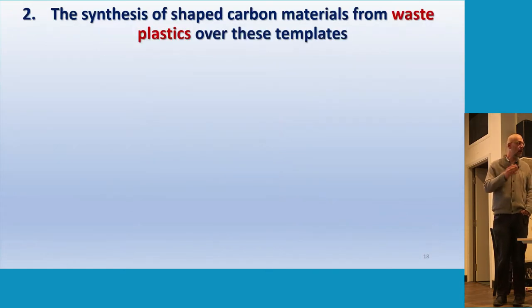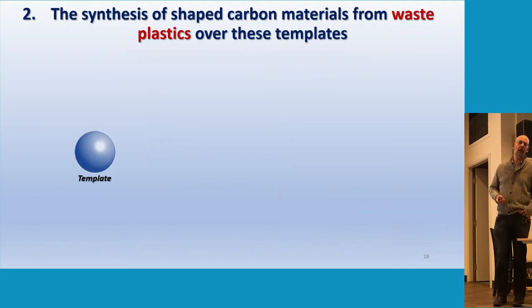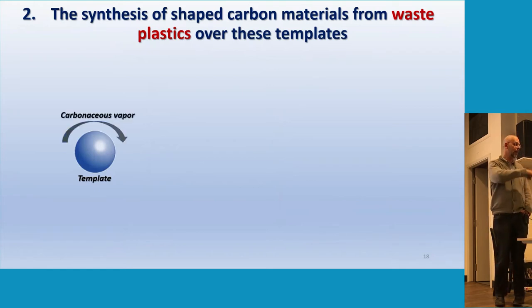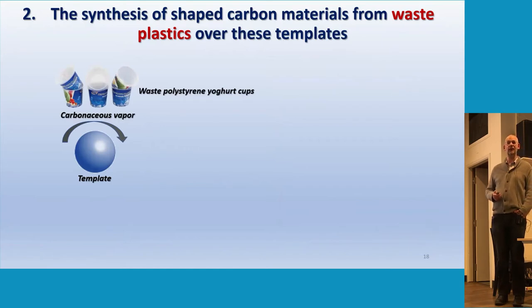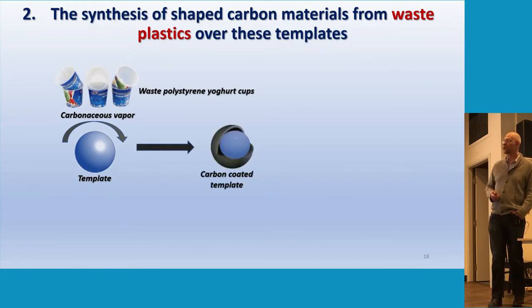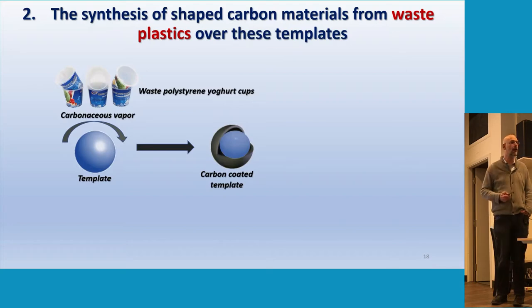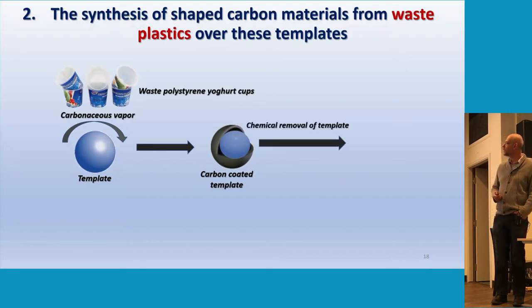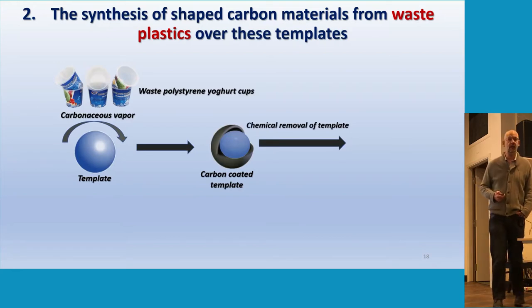The next step is to actually make these carbon structures that we want to use, because we want to put them into other plastic materials to make composites for functional reasons. What is a template? Well, I said to you it's a shaped material. In our case, the copper carbonates are known to form either micro or nanospheres. So you take the template and you pass a carbon gas over it. What we found before in previous research in the laboratory is that you can use waste plastics as the carbon vapor. We use polystyrene. This is an NSERC funded project that we did. And when we did that, we were able to coat the template with carbon. In that case, it was a calcium carbonate, but we're going to do the same thing now with the copper carbonate.